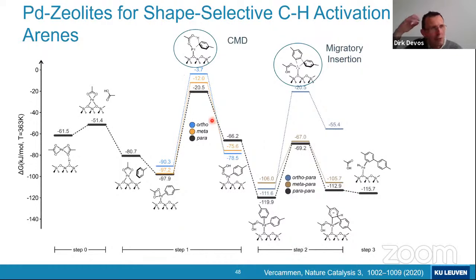This still leaves us with the question, why do we have this positional selectivity? Well, it seems that at least this first step, the CMD with the palladium coordinated on the zeolite, but also by the acetate, as you see here, favors heavily the para-activation. So it seems that the sterically constrained environment in the zeolite pores really favors this first para-activation of the toluene.